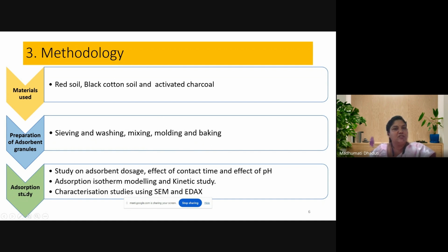And the adsorption study was done to find out the optimum adsorbent dose, and the effect of contact time was checked, and the effect of pH by carrying out the adsorption with varying pH values. Adsorption isotherm modeling for Freundlich and Langmuir was done, and the kinetic study for pseudo first order and second order was done, and the characterization studies were done using SEM and EDAX.